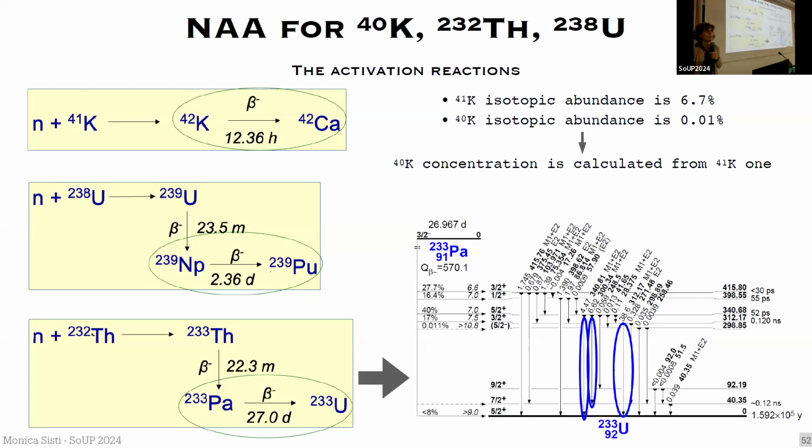Why don't we use accelerators for neutron activation? Accelerators to accelerate what? Protons into a lithium-7 target, then we get a neutron cone with a specific energy. Yeah, this could be another type of activation. Usually, this is not used, as far as I know, for material screening. This is much easier at a research reactor. You have high fluxes, but not so high that they can destroy your material, because this is also a problem that you can have.